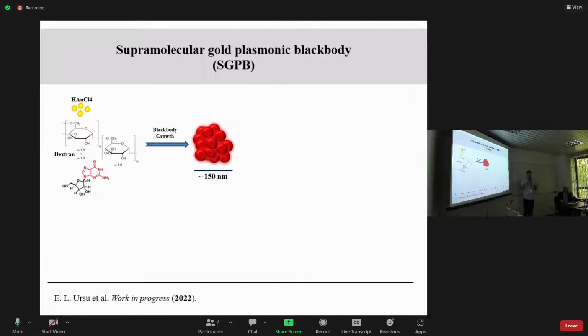Well, it's very similar to what Professor Vekas just said in the case of magnetic nanoparticles, where you have a cluster of the size between 50 and 150 nanometers, and this cluster consists of densely packed small nanoparticles. They are so dense and so close that they absorb all the light from the visible region and infrared region. If any radiation comes on the surface of these clusters, it's immediately absorbed, scattered inside the network, and then eliminated in the form of heat.